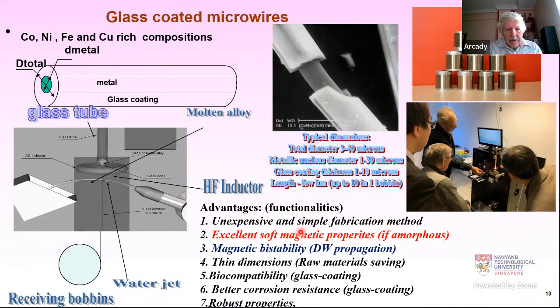For example, one of them is a simple and fast fabrication process. Here, for example, you can see the most modern setup in our spin-off company, which is near San Sebastian. And of course, the most important for this talk are the quite soft magnetic properties, which could be exhibited by these materials if they have an amorphous structure. And these properties are magnetic bistability, which is closely related to domain wall propagation, and also soft magnetic properties and the giant magnetic impedance effect. Another one is thin dimensions. For example, from 1 gram of material, we can produce up to 1 kilometer of continuous microwire. Also, the glass coating provides other functionality like biocompatibility and good corrosion resistance. So these are the advantages of our materials.